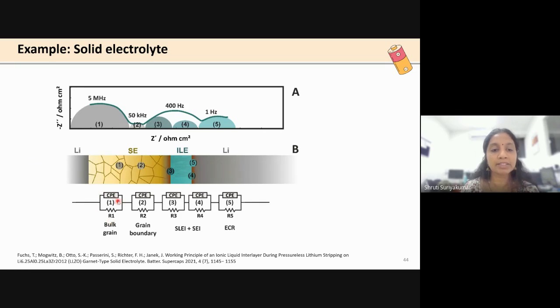Over here, you call it the bulk grain. So when you have a solid electrolyte, it's actually made of crystals packed together, densely packed. So you have a bulk grain here. For a lithium ion to move through it, you will have a bulk grain resistance here, and then there could be some grain boundary resistance. For the lithium to move from here to here, it has to cross this grain boundary. So the grain boundary resistance will be there, and then from this solid electrolyte to the liquid electrolyte, if ionic liquid, it has to go. Again, there will be a double layer kind of a process here. This is again a CPE, double layer with an electrolyte and electrode, and then there will also be an ECR, a charge transfer kind of associated phenomena. So this is what it looks like.